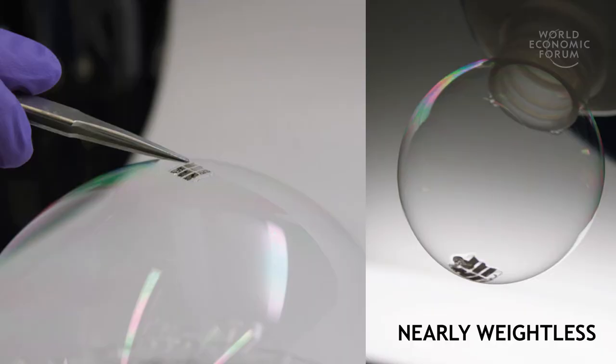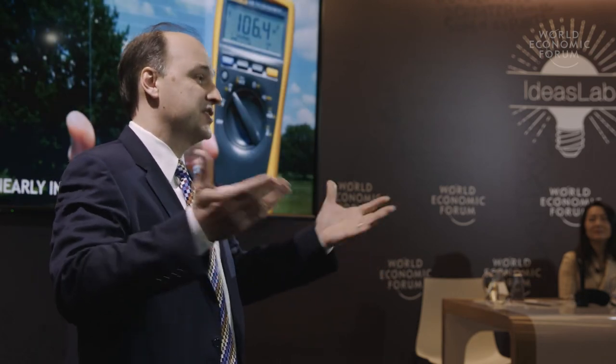This particular piece of paper still has most of its useless weight in the paper itself. Can we thin it down? Yes, we can. This solar cell is so light it can sit on top of a soap bubble. It generates six watts of power per gram of the cell — or six kilowatts per kilogram. As a thin film coating, it's an additive surface that will make any surface active.